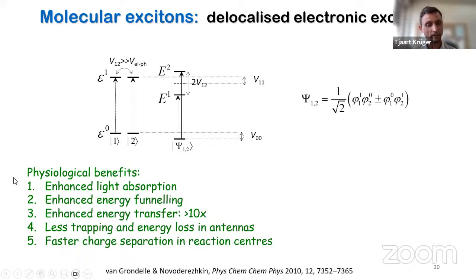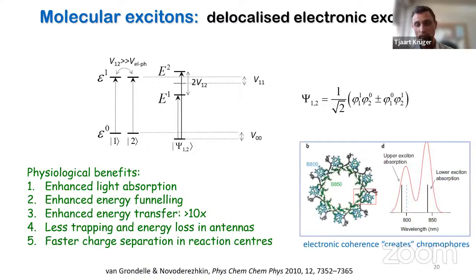So firstly, you get enhanced light absorption, and that is mainly because of this energy splitting, which is then increasing the absorption cross-section of the system. That is beautifully illustrated by, for example, this system, which is light harvesting complex 2 from purple bacteria. And shown here are only the pigments, the chromophores, so bacterial chlorophylls, which are arranged in 2 beautifully